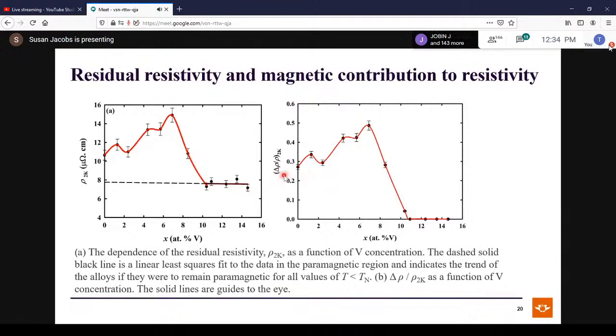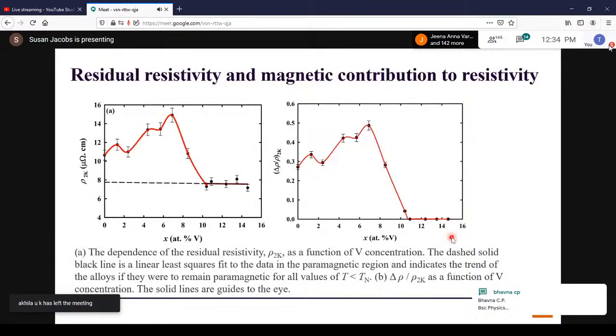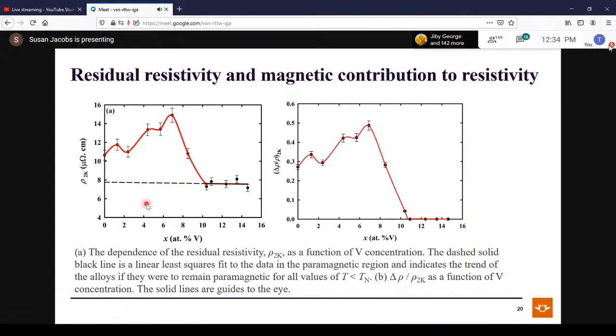And the ratio of the magnetic contribution to resistivity to the residual resistivity shows the same trend: it increases up to about 6.9, close to 7, and then drops sharply through the critical concentration and remains flat in the paramagnetic region. This dotted line over here is the trend of the curve if it were to remain paramagnetic for all concentrations. It's a fit. The solid red lines are just guides to the eye.